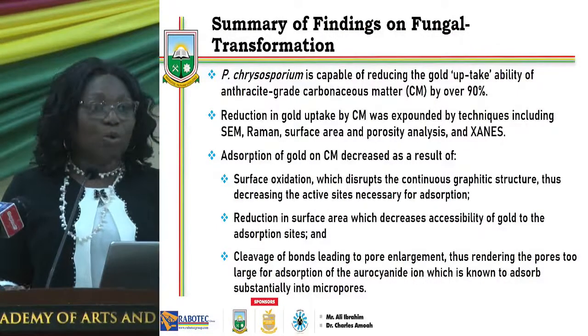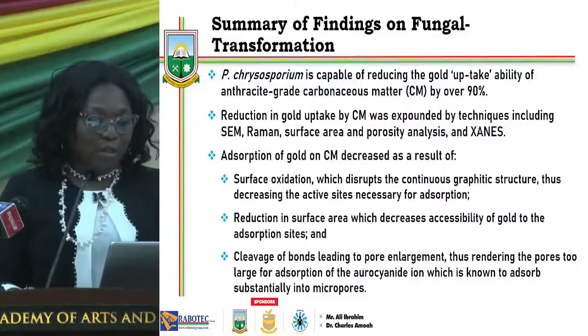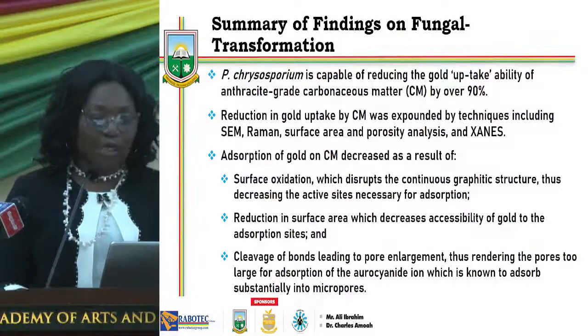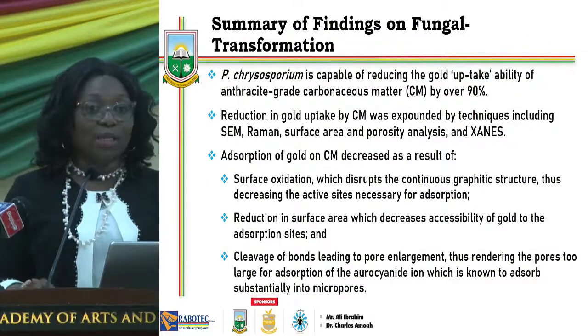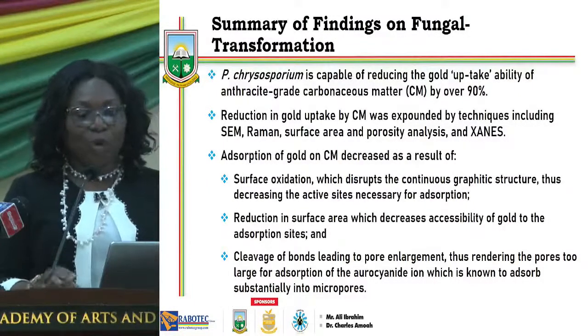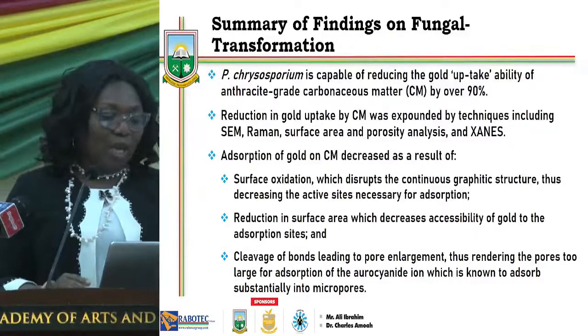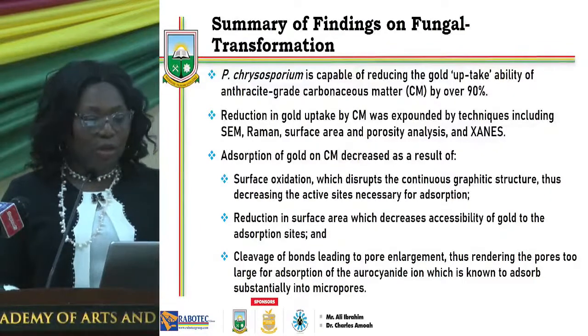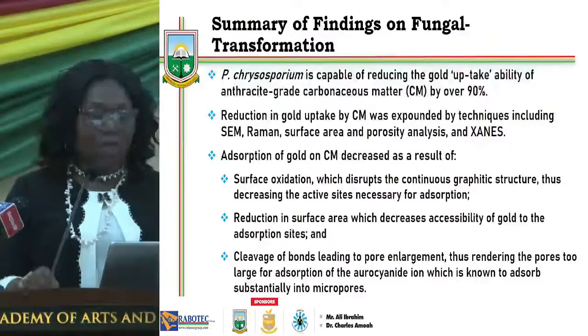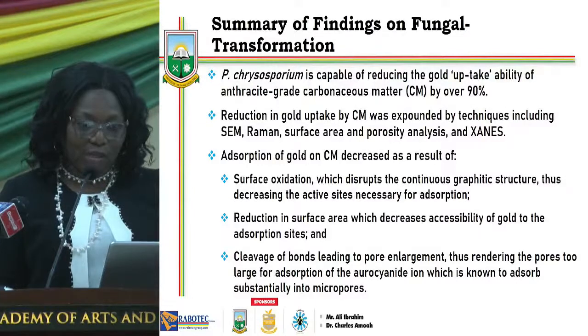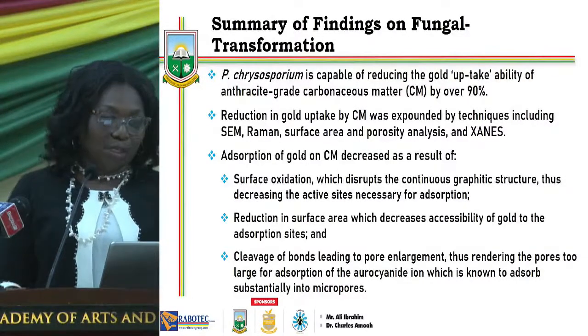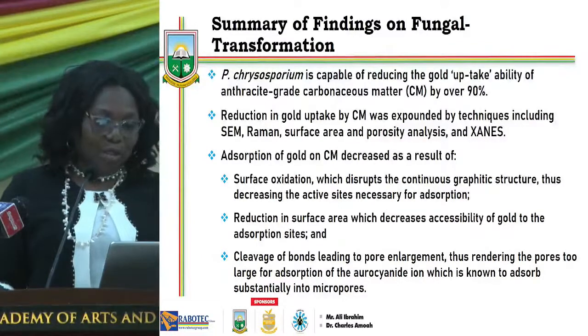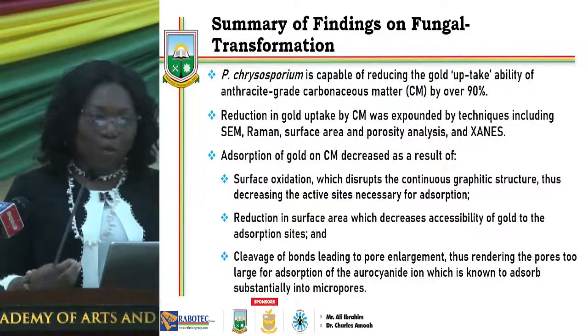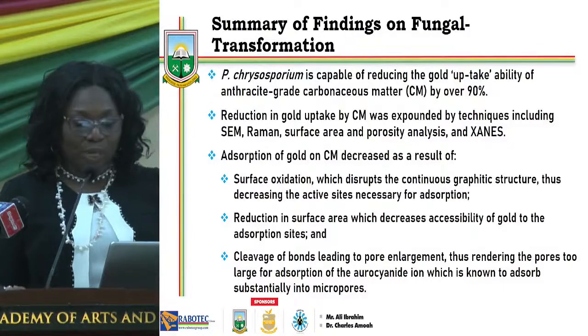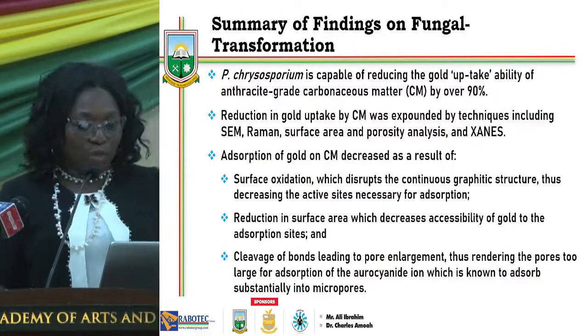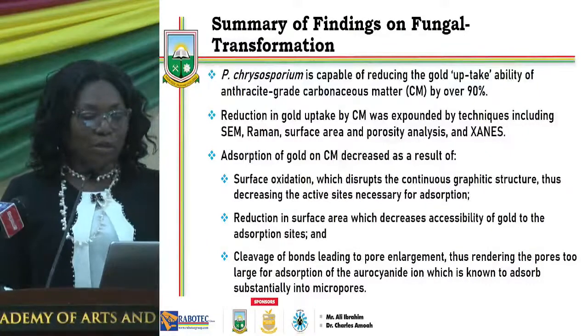which disrupts the continuous graphitic structure, thus decreasing the active sites necessary for adsorption. We have reduction in surface area, which will decrease accessibility of gold to the adsorption sites. And we have cleavage of bonds, leading to pore enlargement, and therefore the smaller pores that are most important for gold adsorption will reduce, and that will reduce the ability of the carbon to adsorb gold.